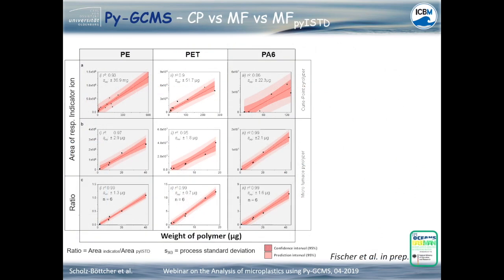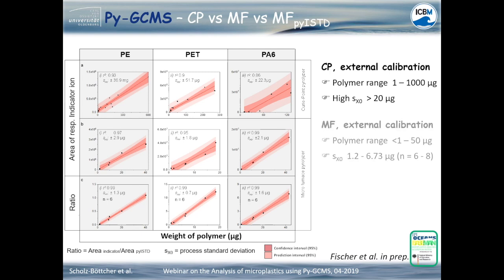This slide compares the calibration between both systems for 3 polymers. The Curie-point system allows a calibration up to around 1 milligram of a single polymer, but it shows very high process standard deviations. For the microfurnace system, the maximum of a single polymer is much less. Weights much higher than 50 microgram lead to saturation effects in some cases and should be avoided.